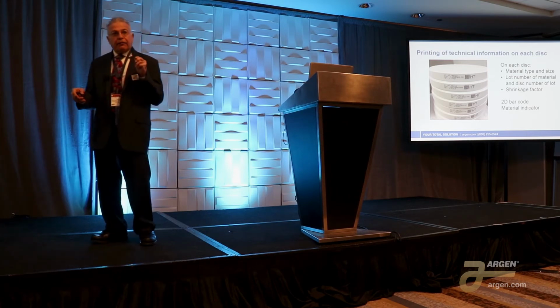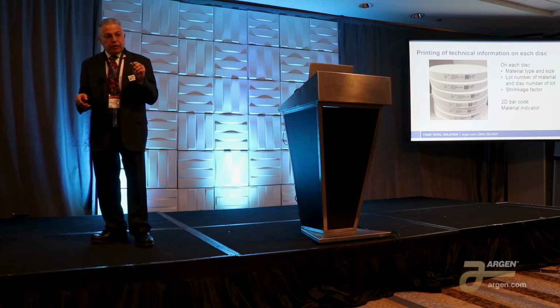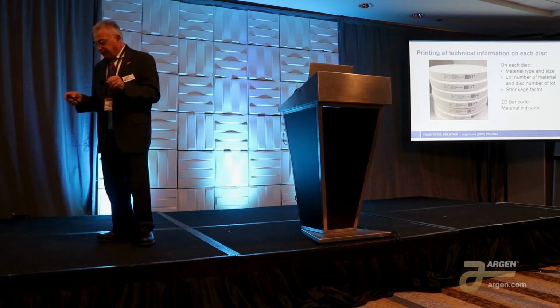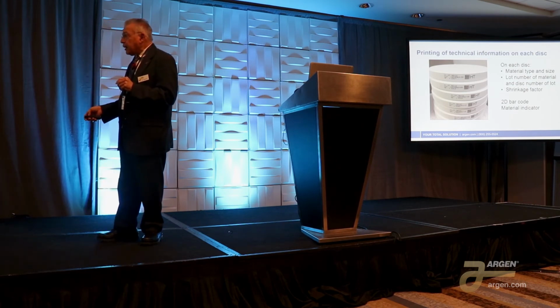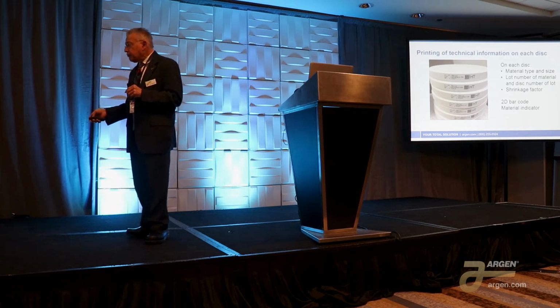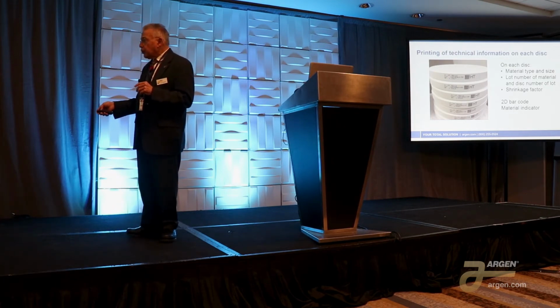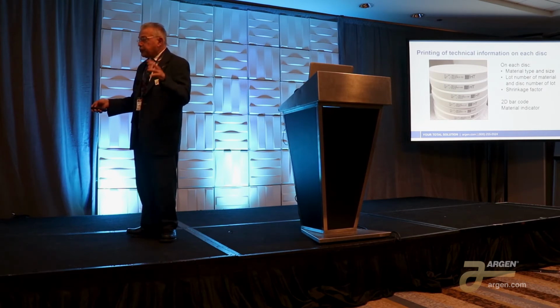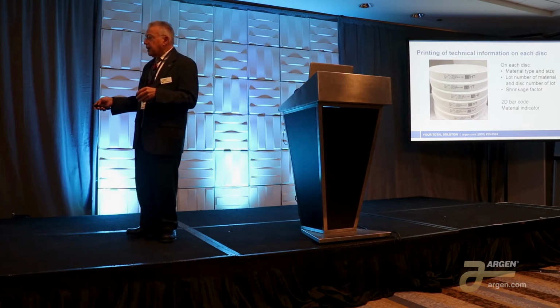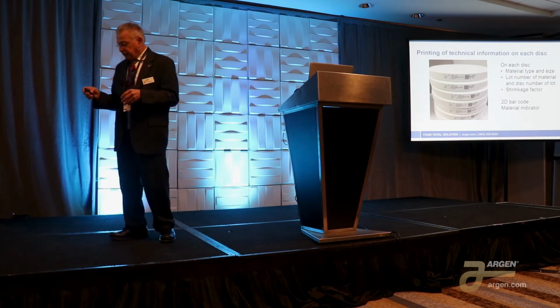So we keep track of each disc. Most other companies just keep track of it by lot. And we calculate the shrinkage rate for each disc as well. And as you can see, the shrinkage rate only changes in the 4th decimal place. Very consistent. We also put on a 2D barcode, which has all of this information plus more for traceability, and then finally the material indicator in big type.